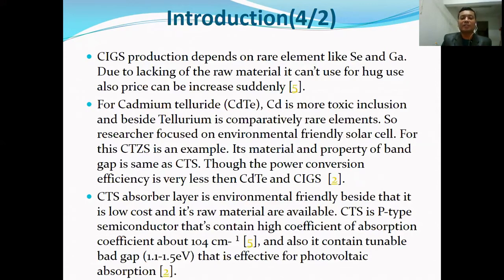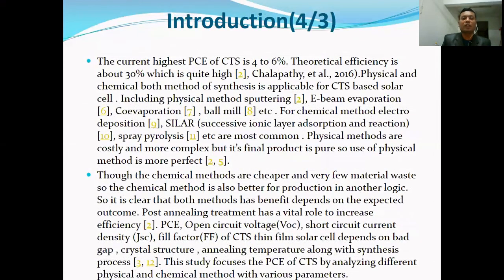The CTS absorber layer is environmentally friendly and low cost, and its raw materials are available. CTS is a P-type semiconductor that has a high absorption coefficient, on the order of 10 to the power 4 per centimeter. It also has a tunable band gap of 1.1 to 1.5 electron volts, which is ideal for a photovoltaic absorber. The current highest efficiency of CTS is 4 to 6%. Theoretical efficiency is about 30%, which is quite high.